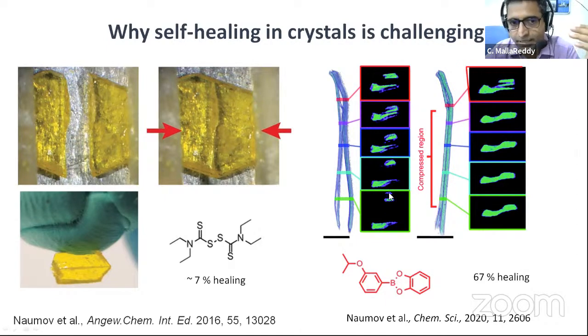So these are very soft materials. This one is really soft, and then you have to put it for hours. I think it is 24 hours if I'm not wrong. And then you still see a big crack here, and this remains crystalline, but its crystallinity is not maintained here, so it really gets damaged. But it is again a very important contribution, and this also inspired us in some way.